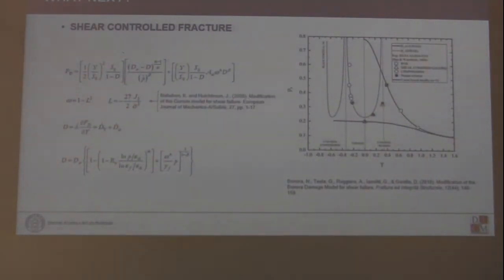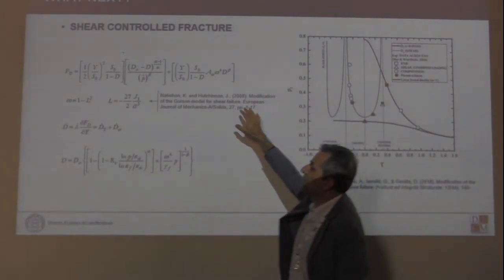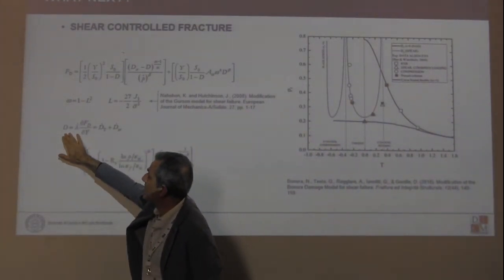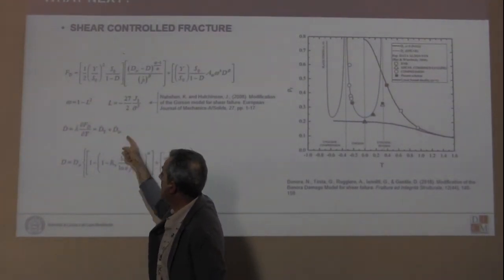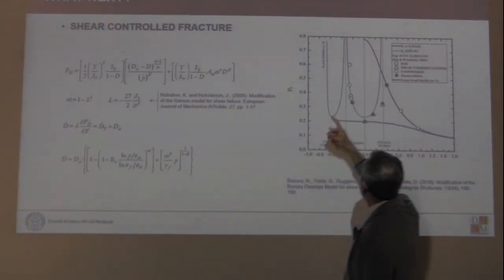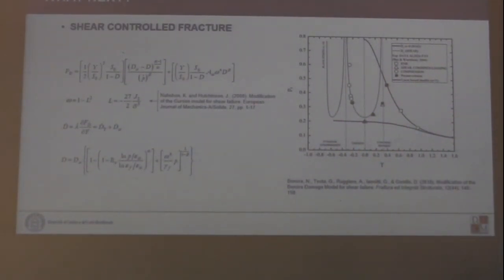Actually, there is evidence that this behavior can be observed in different materials. This is for Weldox, and a number of fancy samples have been proposed to test material in this condition. We just recently extended the original damage formulation that I proposed in 1997 in order to account for shear controlled fracture. We succeeded in a very simple way, modifying the damage dissipation potential, to obtain a damage rate equation which has stress triaxiality controlled plus load angle controlled terms, and you can predict failure, or the cusp in the failure locus plot.